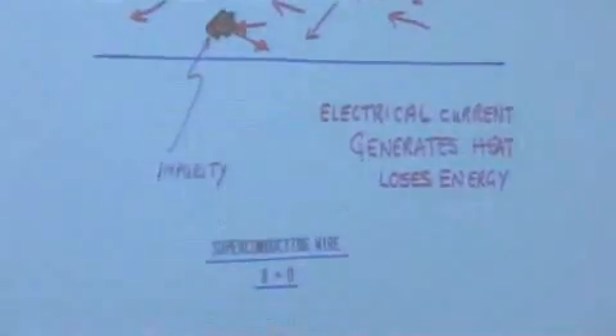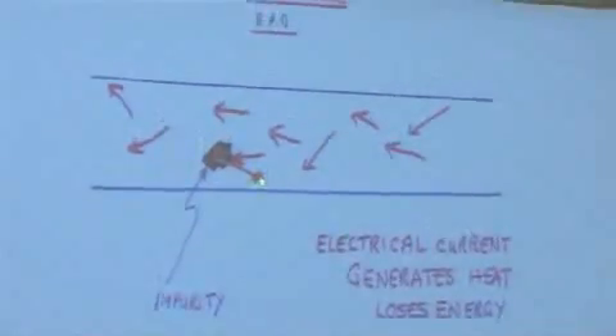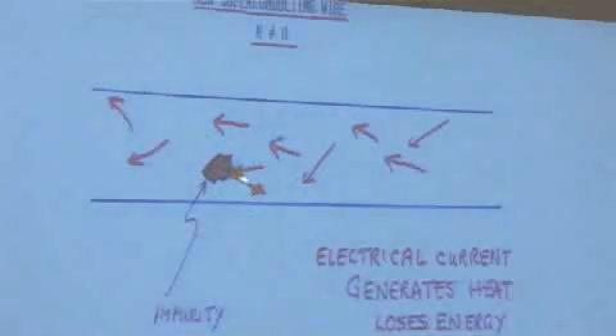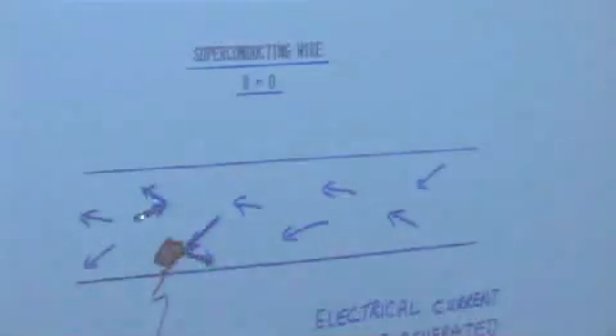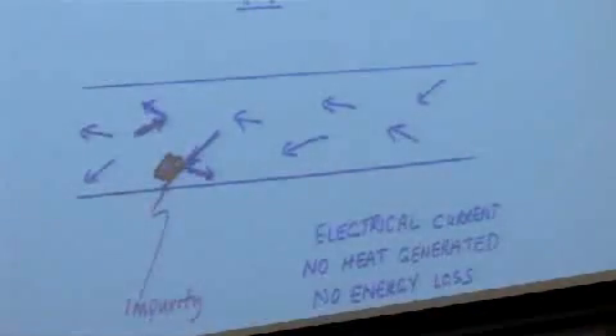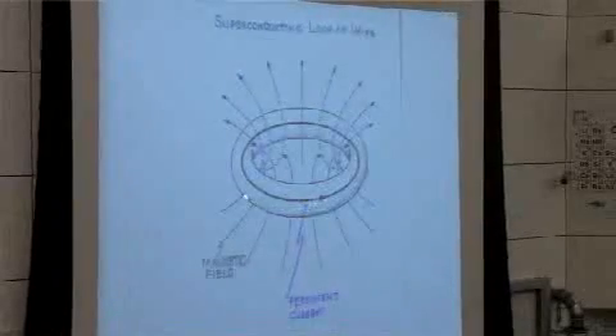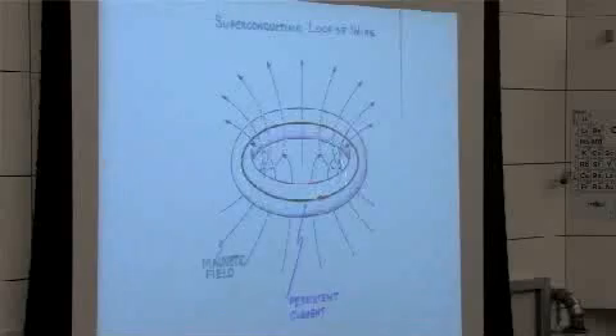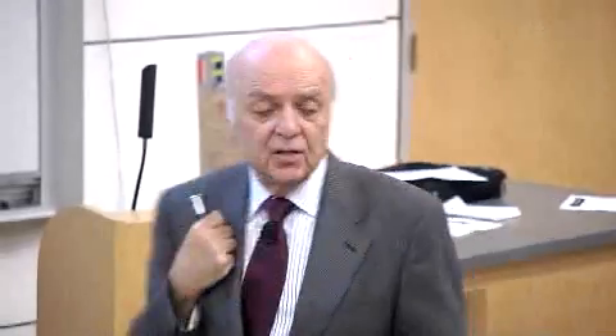Now, one of the things that happens is no resistance. Another thing that happens is that you don't lose any energy because there's no resistance if electrons go down a wire. Now, in your toaster, you want electrons to lose their current. You want to heat up the wire to make the toast. So electrons traveling down an ordinary wire will bump into impurities and into vibrations and so forth, and it'll generate heat. But electrons in a superconductor will go through with zero resistance. Not a little resistance, zero resistance. And as they come down, when an electron bounces off an impurity, another electron bounces the other way to take up its loss. And I'll show you this in a moment. The curious thing is that if you get a ring and you make that ring superconducting, not only will the electrons travel around with no resistance, if you keep it cold, it'll keep going like that for the age of the universe. It just won't decay.